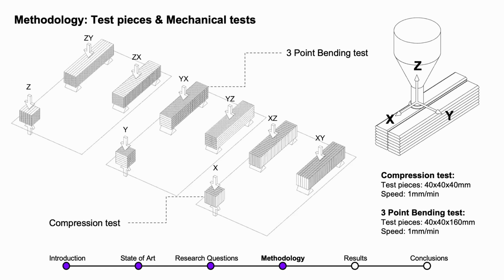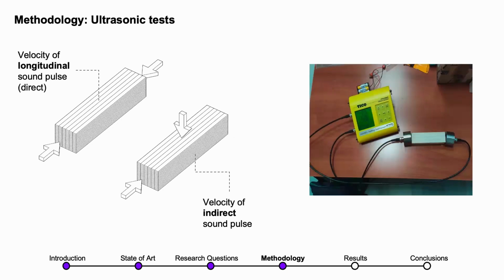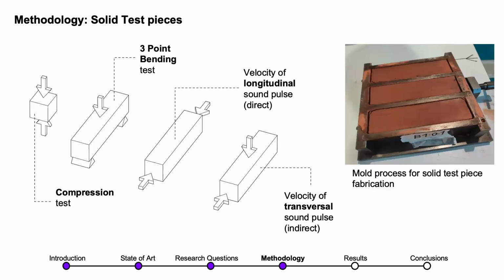This is what one of those batches looks like. We have 3 different compressive strength test pieces and 6 different three-point bending test pieces. For all of those pieces, we carried out the ultrasonic test for the longitudinal speed and the indirect speed. And all those tests were also carried out on molded test pieces, to compare the 3D printed pieces with the non-3D printed ones.